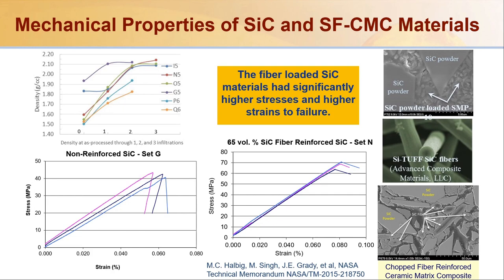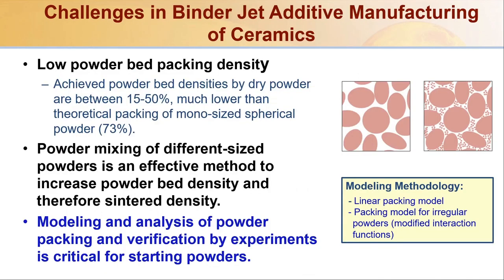But the point here is that having these fibers added during this process is very beneficial to the overall behavior of this composite. So in the previous efforts, with those irregularly shaped powders, we were not able to get very high packing densities. So we thought that maybe we should try different types of powders and see if we can increase the powder bed density and therefore the sintered density, as well as try to do some modeling and analysis of powder packing and verify it by experiments, which is going to be pretty critical.